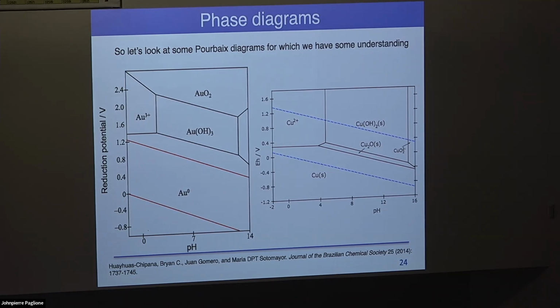Another example is copper. So if you think about the Statue of Liberty, it's copper, right? But is the Statue of Liberty copper colored now? No. And the reason for that is in the stable region of water, you have all these different copper species that are available depending on the pH. So if you have acid rain, or maybe somehow basic rain or something like that, you have all these different species that the copper on the surface can convert to. And that's why, for example, the Statue of Liberty has all this patina, from basically the corrosion and the passivation of the different copper constituents on the surface of the Statue of Liberty.